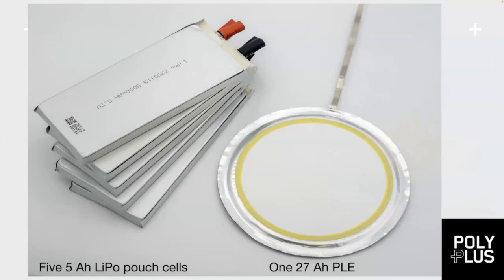So let's look for a second at this technology. What you see here are actually electrodes we're making now on a manufacturing line that is installed in Berkeley, which will eventually be moved out of state as you start to actually scale this technology. That's a 27 amp hour protected lithium electrode. So it's a lithium electrode stable to water, stable to a variety of chemical environments. And on the left, you can see a stack of lithium ion cells, 5 amp hours. You can just get a sense of scale here in terms of the extremely high capacity density and energy density that's available in these types of electrodes.